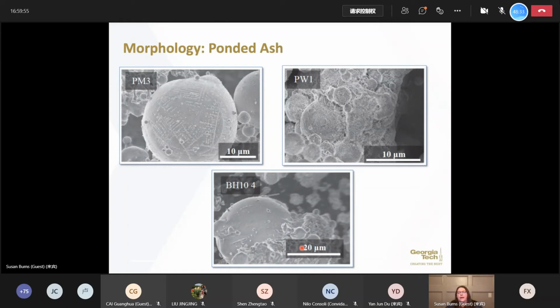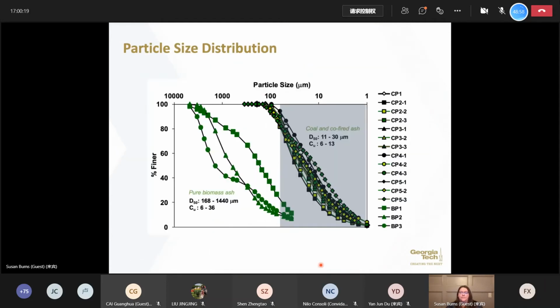It makes sense, right? Because we know that when we have ash deposits, if we look at the groundwater, sample the groundwater around those ash deposits, we'll see characteristic plumes with dissolved constituents, things like boron and sulfate, chlorides. We know those all leach from the pond, and that leaching effect is going to leave ash particles here, which have a changed morphology, somewhat changed chemistry as well.